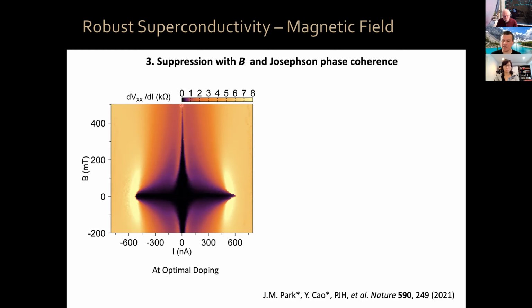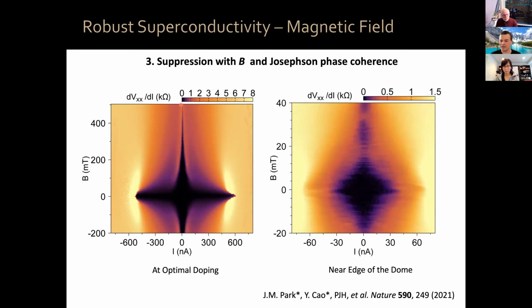Okay. If you now change your density close to the edge of the superconducting dome, where the system is starting to break into superconducting islands separated by non-superconducting islands due to disorder, for example, then if you measure your critical current as a function of perpendicular magnetic field, you can observe these Fraunhofer-like oscillations, which tells you that there is Josephson phase coherence because of these superconducting islands, which are coupled by non-superconducting regions. So all of these 3 features that I told you show that this is a robust superconductor.